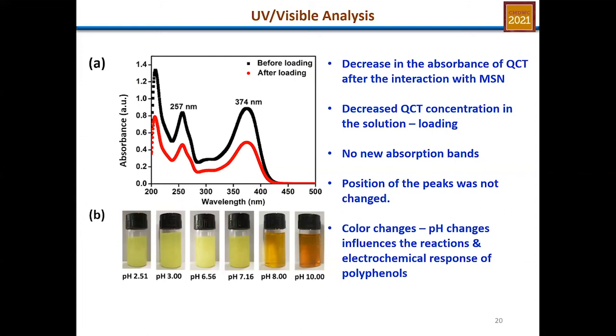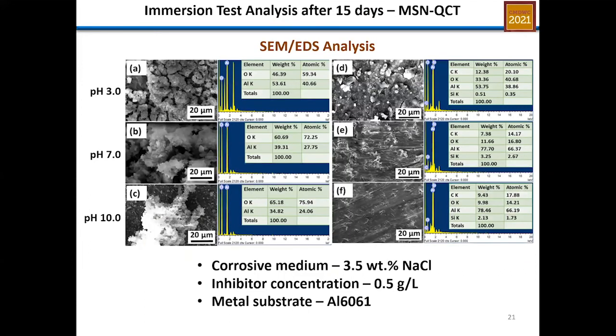We carried out the immersion test for 15 days using the nanocomposite that we had obtained, in 3.5% NaCl. We used 0.5 gram per liter on aluminum alloy 6061. The aim was to find out which pH would be more effective in the release and reaction of the inhibitor from the nanocomposite in protecting the metal substrate. And we realized that pH 10 provided better inhibition on the metal substrate.